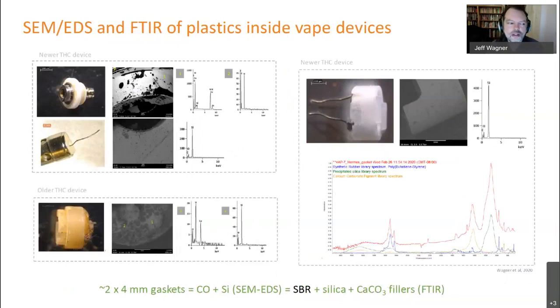Here is another example of polymers. These are rubbery gaskets of various different types you see in different devices around the battery contacts or to seal the end cap or around the heating element itself, which is what you see on the right. We did FTIR on that. In almost every case, we saw basically just a silicon peak in addition to the carbon and oxygen. And FTIR confirmed that is likely due to silica additives as well as calcium carbonate additives in some cases, and a polymer ID of styrene butadiene rubber. Again, any danger of liberating styrene would be dependent on exactly how hot it gets inside these devices. So that's the big question mark right now.